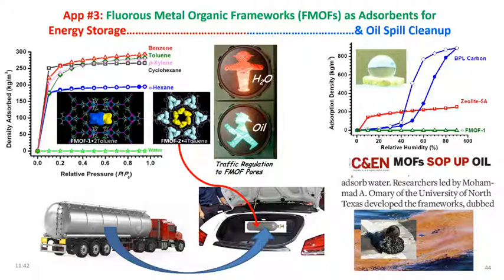Theoretically it does, but experimentally, as you can see, it still has some oxygen groups, some aldehydes, ketones, alcohols, acid groups on the surface. Even small amounts still accumulate to something large enough. That is even in the humidity, in the gas phase. And with real water, we have humid days, even in North Texas, with more than 80% humidity. Whereas our materials, we can soak in liquid water for a week, for a month, take it out, and there's absolutely no water in the pores. They're as pristine as the porous material crystal structure has.